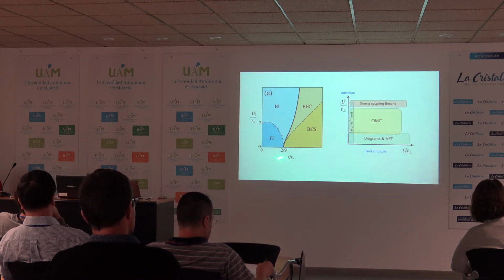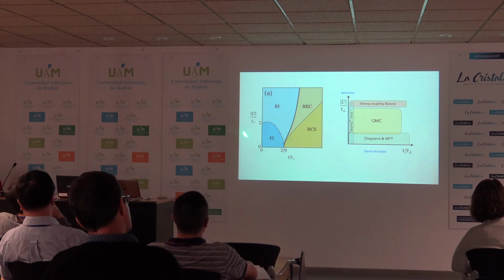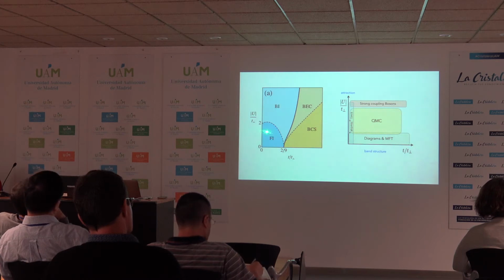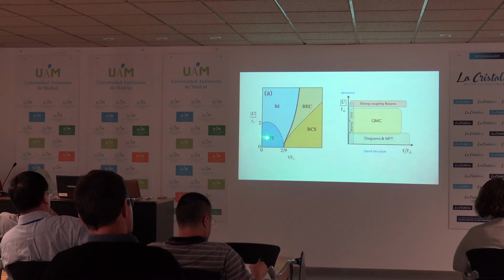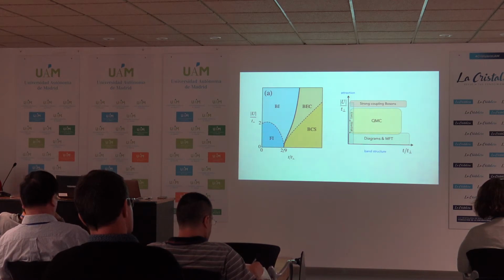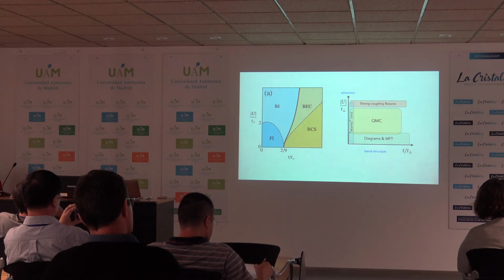You have 4 phases. This Fi is the Fermi band insulator. So think of a cut going like this. At small hopping, you have a Fermi band insulator. And what this picture says is that you cannot directly go from a Fermi insulator to a BCS superconductor. You necessarily will go through 2 intervening bosonic phases. The slivers may be very tiny, but there will be a regime where at some finite attraction, the Fermi insulator will become a Bose insulator, and I'll tell you precisely how we define that. And then there will be a transition to a BEC, and then a further crossover into a BCS superconductor.